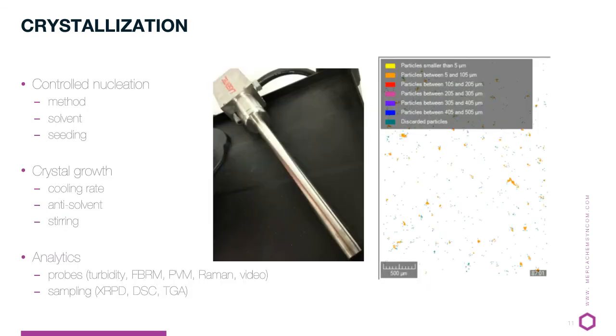And crystallization is all about control. So a controlled nucleation, where you know the method, the solvent, and whether you have to use seeding. You control your crystal growth by a certain cooling rate, by an anti-solvent addition, and the amount of stirring that you apply. It gives certain results. And these results are analyzed either in situ by using probes, or by sampling, and you can analyze the material afterwards.